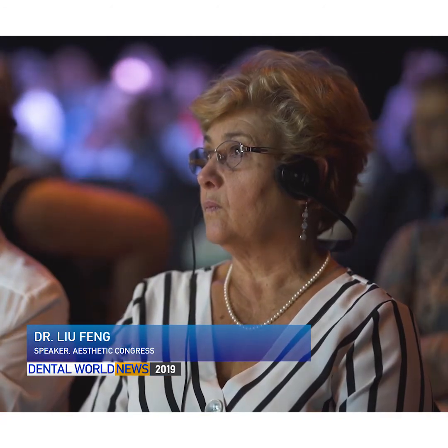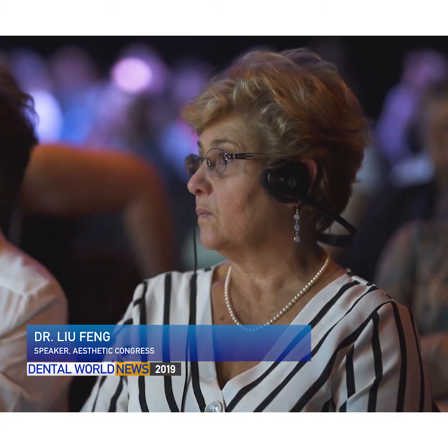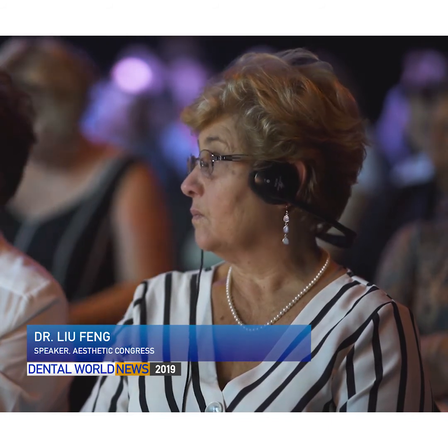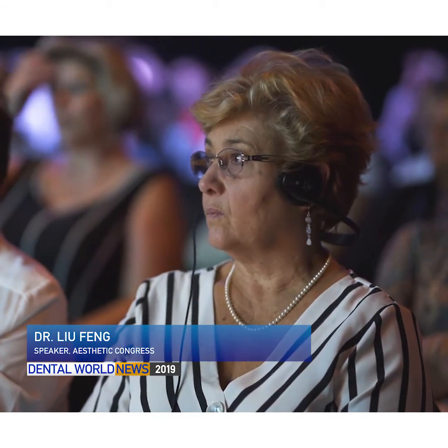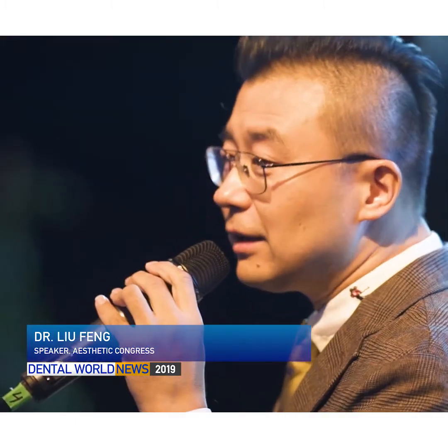And the high multi-layer, high translucent zirconia can make the full zirconia restoration. It can give us a very beautiful and very strong restoration. And if we want to make it better, we can use outside stain. Or sometimes we cut a little bit and use a porcelain veneer, but only on the buccal surface. It can make it more beautiful without damaging the strength. So I prefer to use it.